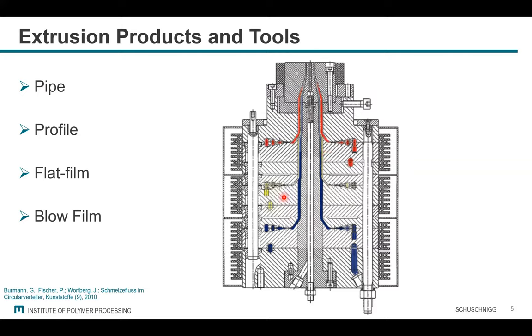And there are now dies with up to 11 different layers, each acting as a barrier against certain properties. As all these polymers, as Ivica told before, have different viscosities, the flows have to be optimized in between the layers where they get together, because polymers with the low viscosity try to surround the polymers with the higher viscosity. And so therefore you have to be really careful to select the materials and select also the whole die design.